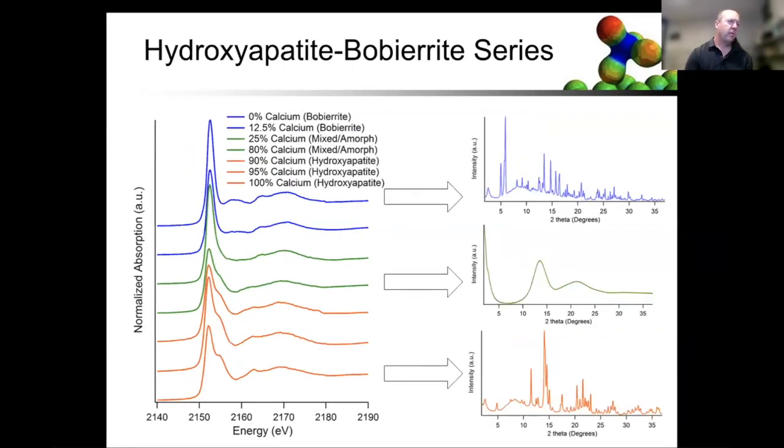The other thing that we learned out of this system is if you go to a higher pH and you look at apatite as your phase, that apatite either will make amorphous calcium phosphate, which still seems to have largely the apatite structure. And so the implication is that amorphous calcium phosphate is actually just nano apatite, just very, very small particulate size apatite. And that's a transient phase that turns into apatite fairly rapidly.